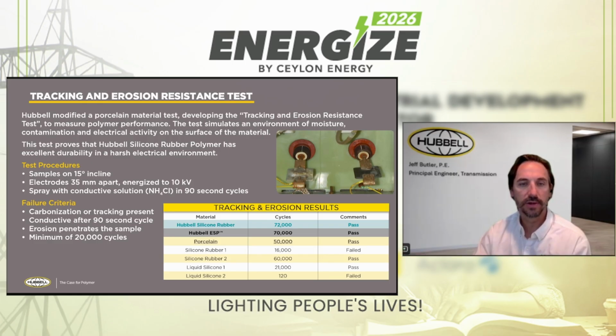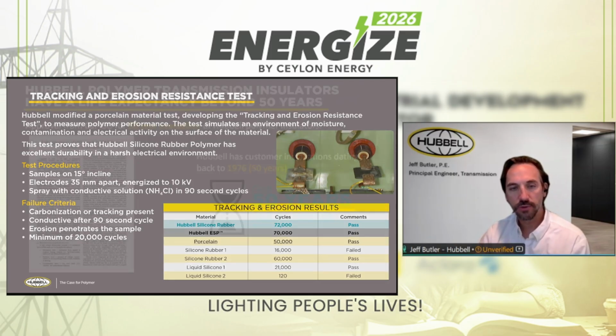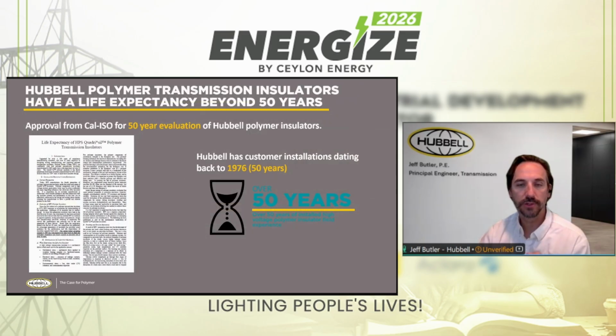And you can see that for porcelain, 50,000 is the target, and the two Hubbell materials exceeded the porcelain. The silicone rubber two, as well, did exceed the porcelain minimum. And then you can see the ranges of the others. Again, very interesting to note the dramatic difference between the performance of what should have been similar materials with similar performance.